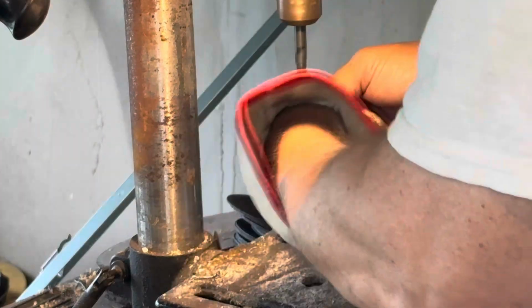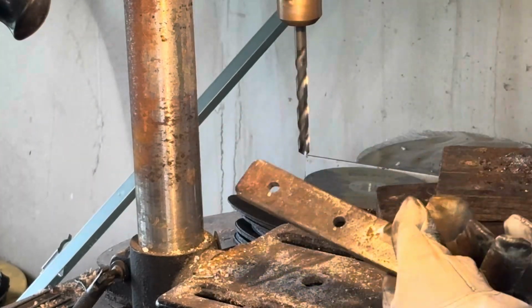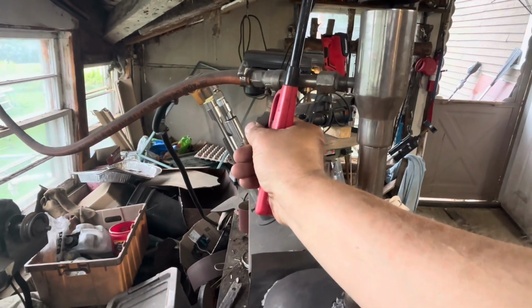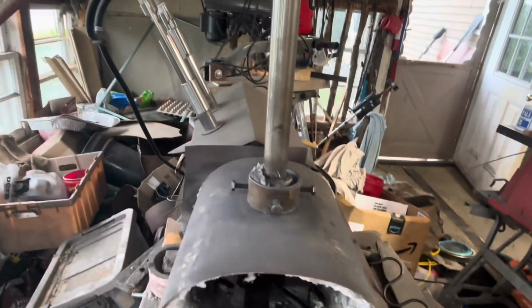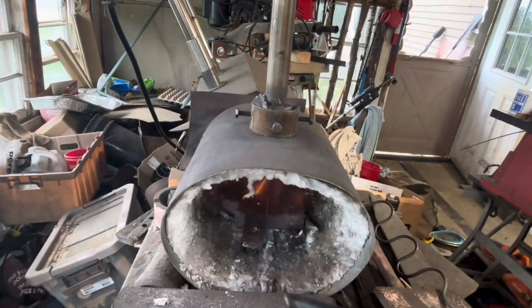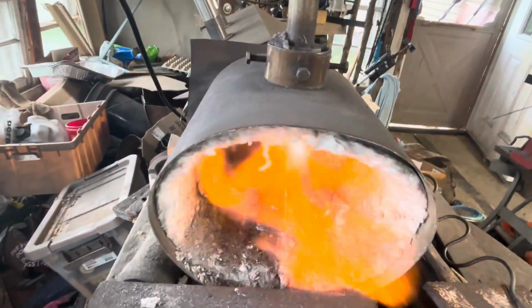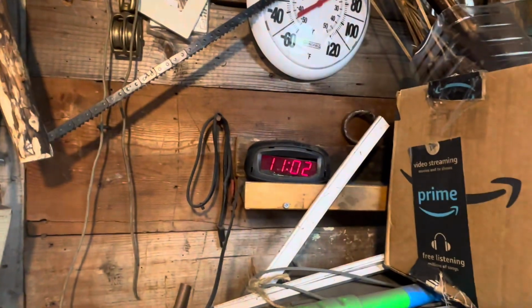If I couldn't drill through it, I would have to put it in the forge, heat it up to non-magnetic, and then let it cool down slowly. That's called annealing, and that will make the metal soft enough to drill through. I'm checking to see if the brass rod fits the hole, and now I'm going to start the heat treating process where I'm going to quench harden it. And I noticed it's 1:02, and it's exactly an hour after I started this project. So I'm making really good time by going simple.